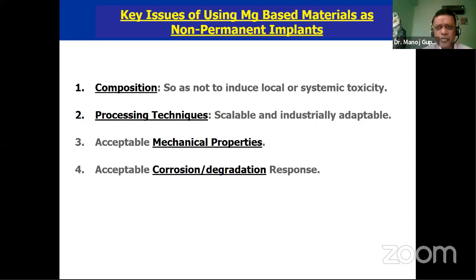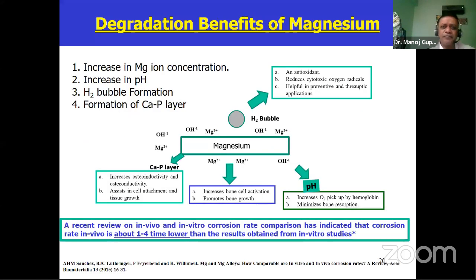So what are the key issues of using magnesium-based material as a temporary implant? We have to be careful about the composition - we have to add elements that do not create local or systemic toxicity. We have to ensure these materials can be processed in ways that are scalable and industrially adaptable. We can do the work in the lab, but at the end of the day, if it has to reach a common man, the processing technique should be scalable and not very expensive. It should have acceptable mechanical properties, since when used as an implant it has to have good mechanical properties. And of course it should have good corrosion and degradation response, which can be tailored based on the healing response of the typical injury being handled.